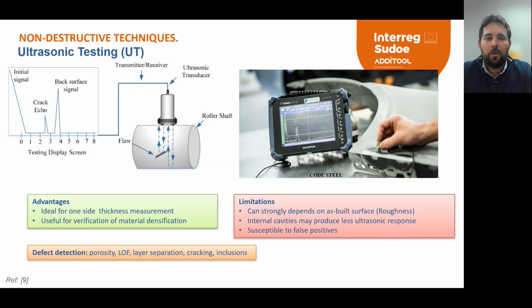So let's start with ultrasonic testing. In ultrasonic testing, an inspector will use a probe or some kind of transducer to send sound waves, as you can see in the schematic view here, through the material they want to test. If there are no defects in the material, the sound waves will pass through. But if the sound waves hit a defect, they will bounce off and indicate its presence, as you can see, for example, in this crack echo.